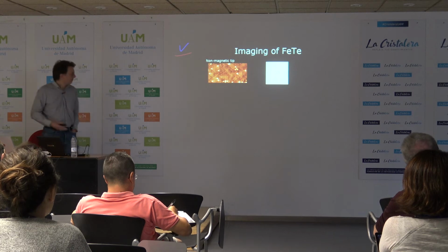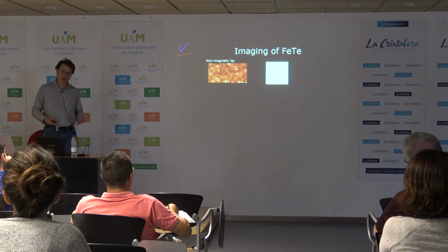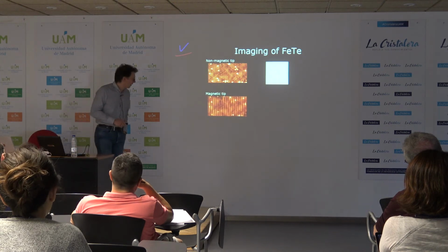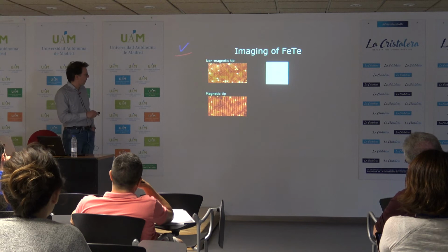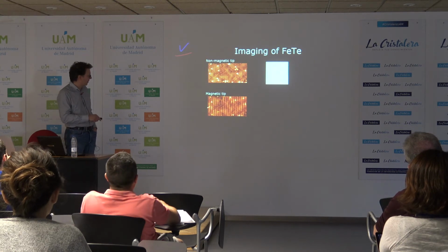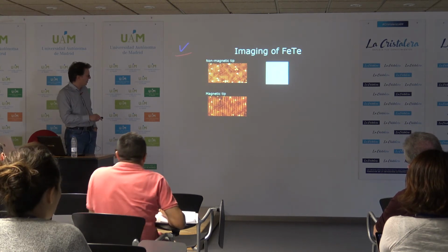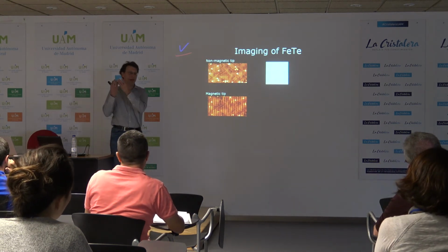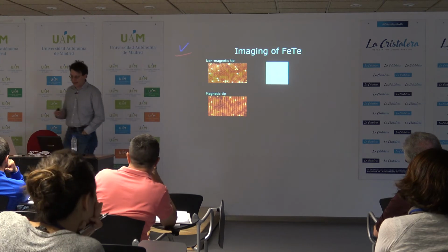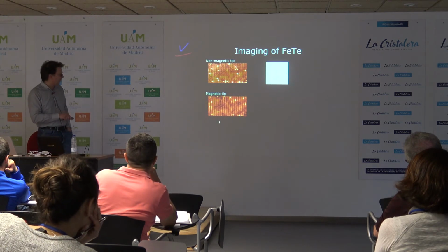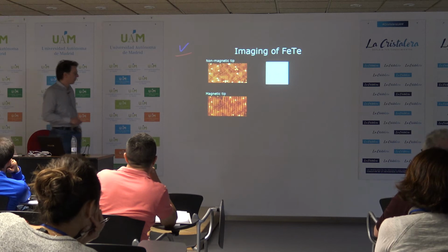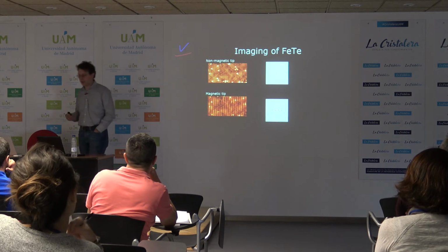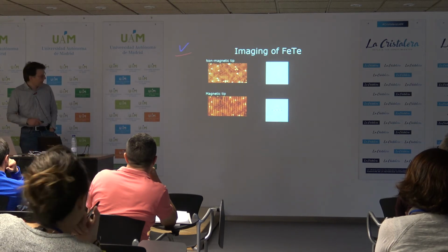And now we can basically use our STM to pick up some of these iron atoms here and thereby render the tip magnetic. Okay. So here you see an STM image where some of these iron atoms are still on the surface, but some of the iron atoms are gone from the surface and they are now attached to the tip, which renders the apex of the tip now spin polarized, and hence we now suddenly see this double stripe order running vertically through the image, and if we take the Fourier transform, we see these additional peaks due to the magnetic order in the material.